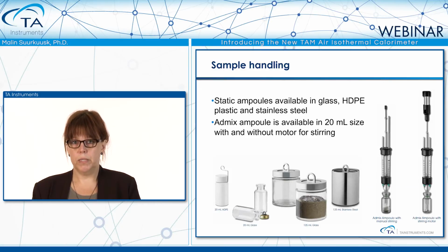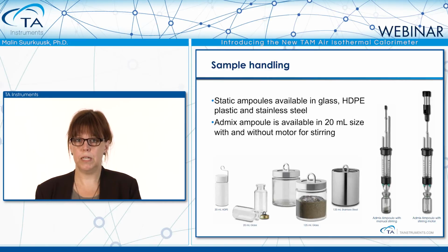And then you have the calorimeter, you have the thermostat, and then you need to put the sample into something, and that's what we call our sample handling system. We have static ampules, which means that we are not doing anything with the sample after we put them in the calorimeter. We put them in an ampule, put them into the calorimeter and measure what's going on. They are available in glass, plastic, and stainless steel, and both for the 125 and for the 20 milliliter calorimeters.